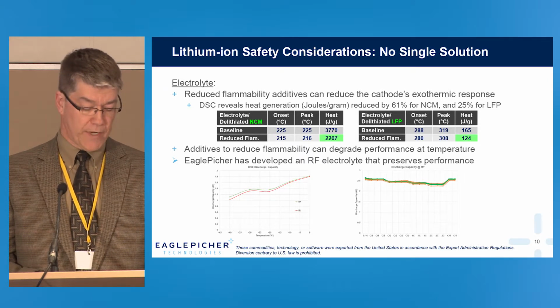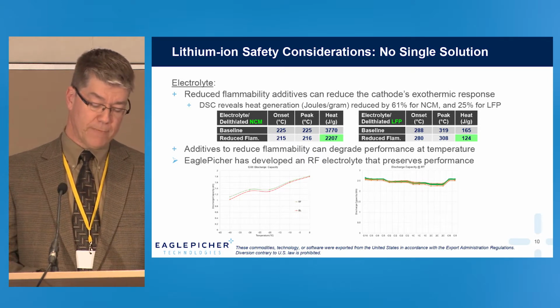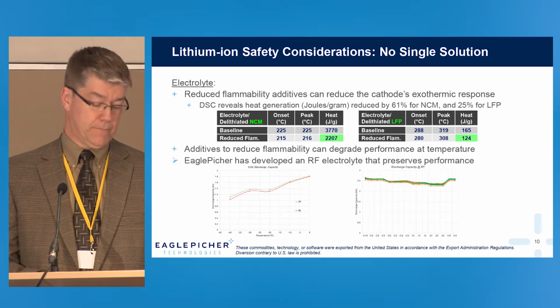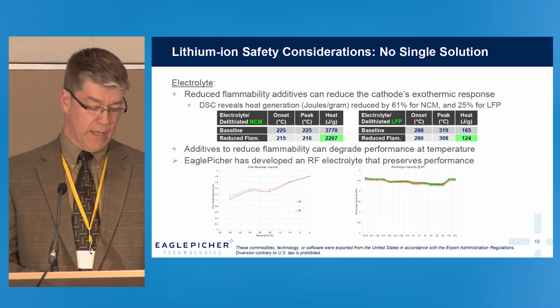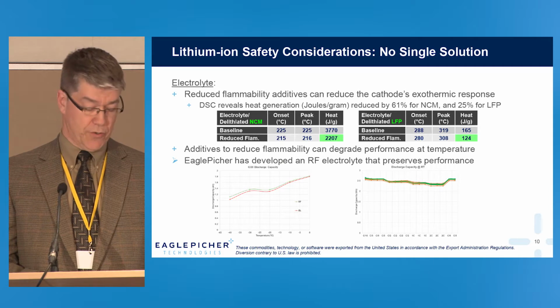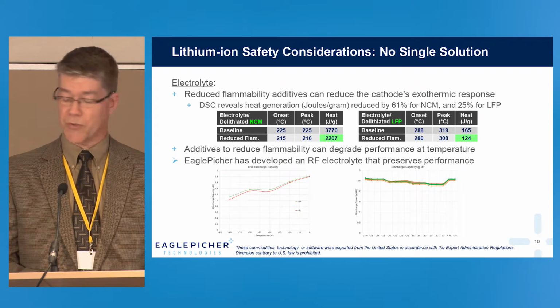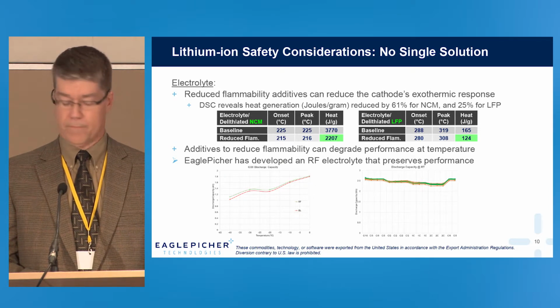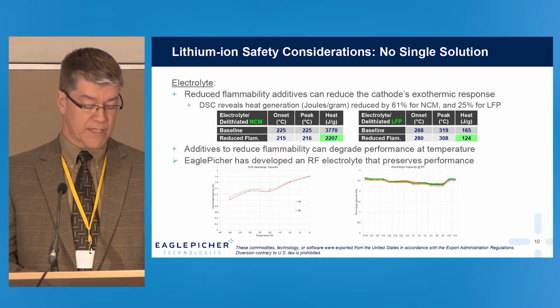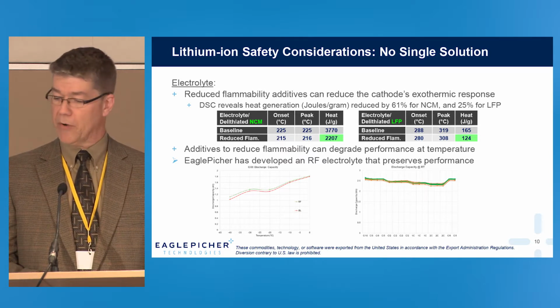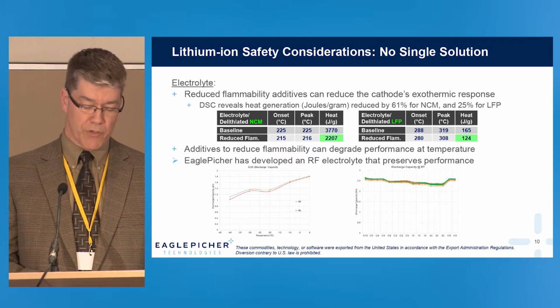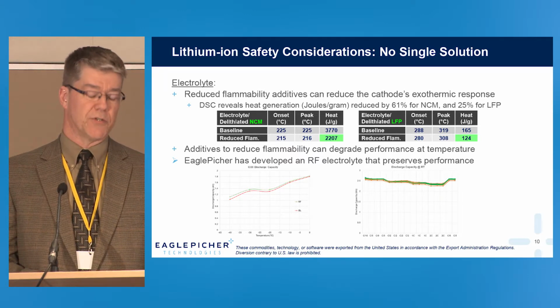EaglePicher has been working to optimize reduced flammability electrolyte that does not degrade performance at temperature. When tested within small cylindrical 18650 format cells, we see the first figure to the left reveals favorable performance of the RF electrolyte versus a baseline for low rate discharge capacity across temperatures down to minus 40 degrees C. When we look at the second figure to the right, we show a comparison between the baseline and the RF formulation up to a sustained 2C discharge rate.